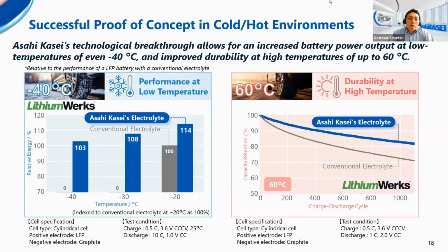Please look at the graph on the left. Low temperature performance was evaluated, and the discharge capacity of the standard carbonate electrolyte at -20 degrees C was set at 100%. Then the relative discharge capacities at -30 and -40 degrees C are shown respectively. Standard carbonate electrolyte could not discharge at 10 C below -30 degrees C, but acetonitrile-containing electrolyte could, even at minus 40 degrees C.